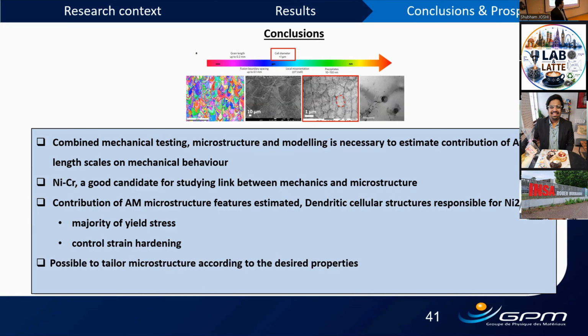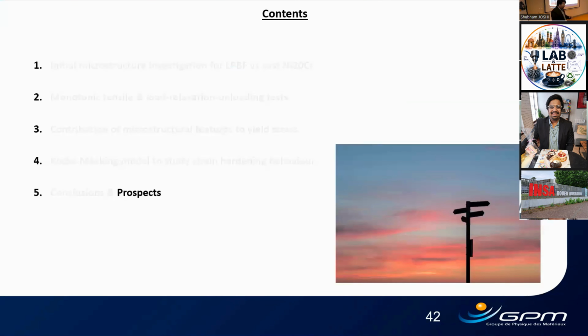It is possible to tailor microstructure according to the desired properties. So depending upon process parameters, you can favor forest dislocation interaction or dendrite dislocation production and so on. And finally, the correction factor and the modeling that we propose pave the way to include this Cox-Mecking model in crystal plasticity modeling of LPBF to understand the plasticity behavior in much more detail. And now the prospects.